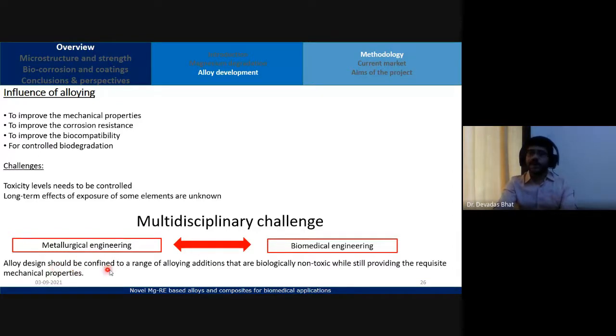So our alloy design should be confined to a range of alloying elements that are biologically non-toxic while still providing the requisite mechanical properties. So like I said before, alloying element like zinc, for example, right? So the solid solution limit is about 6 to 7 weight% of zinc in the magnesium zinc diagram. Now, I add 1 zinc, I add 2 zinc, 3 zinc, 4 zinc, 5, I go up to 6 weight% zinc. Now, if I go with that, I'm going to increase the mechanical properties, right?